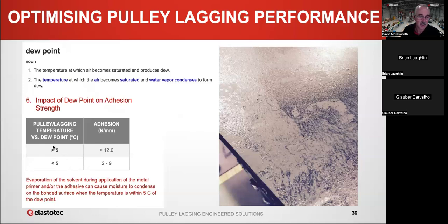And this little table just shows you a difference of the adhesion strength you would get in a humid environment if you were to try and do the bonding close to the dew point, less than 5 degrees. It could be anywhere between 2 and 9 newtons per millimeter, which is very, very low. You could literally peel that. That means you could peel it off by hand. If you're above 5 degrees above the dew point, then you'd get more than 12 newtons per millimeter.